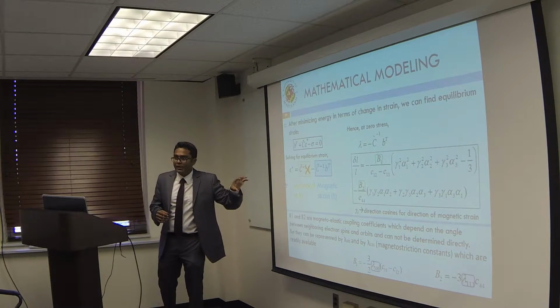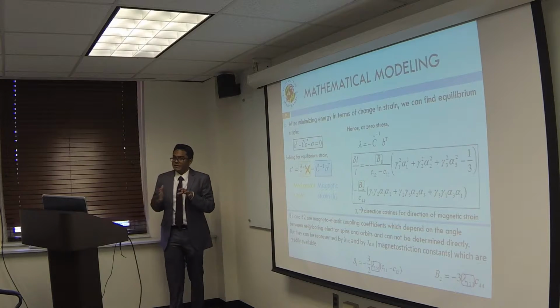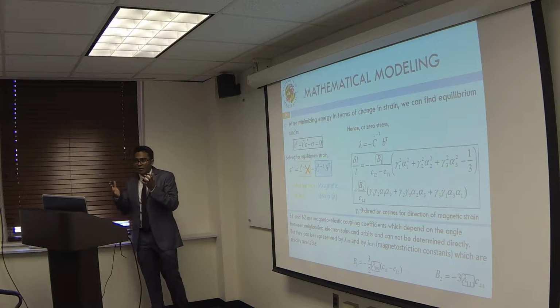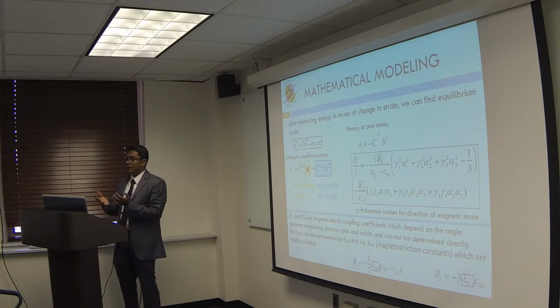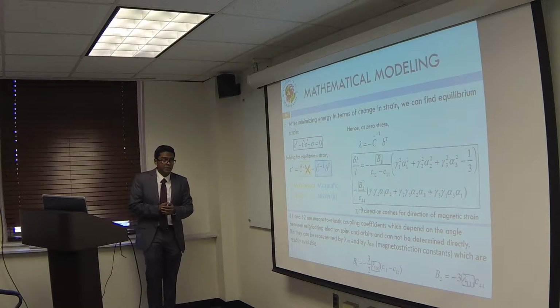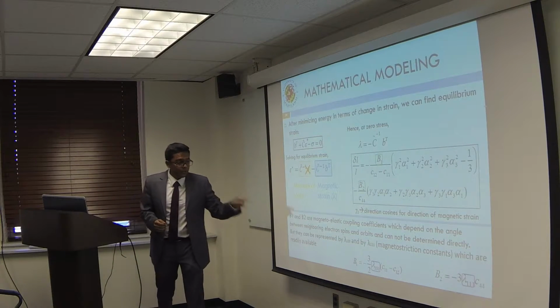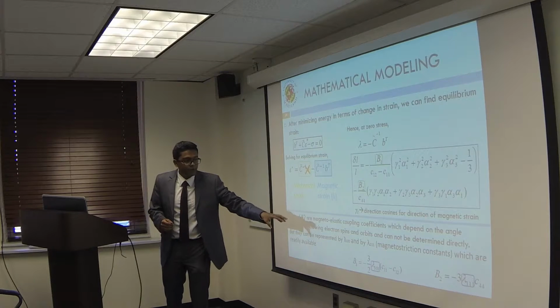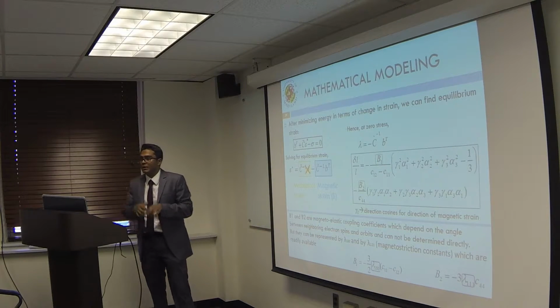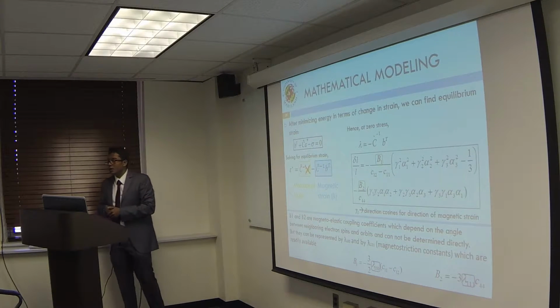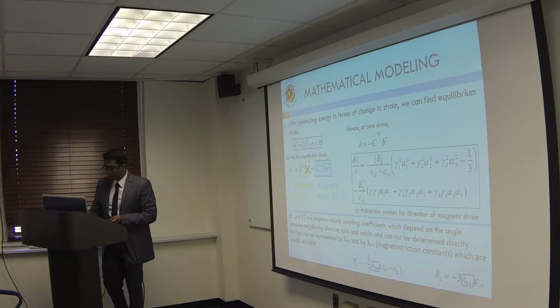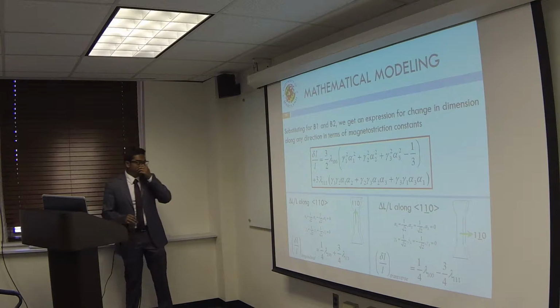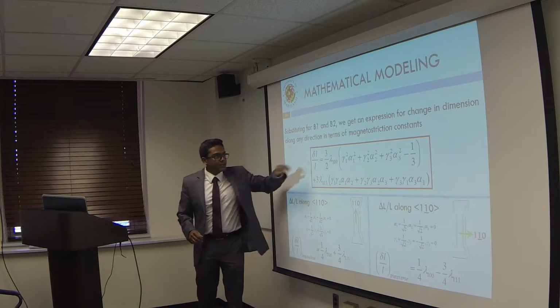The values B1 and B2 cannot be determined very easily because they depend on how the electron spins of neighboring atoms interact with one another. So there's no direct way to measure B1 and B2. But you can quantify B1 and B2 in terms of lambda 100 and lambda 111, which are the fundamental magnetostrictive quantities. So when I plug in for B1 and B2, I end up with this really nice equation here,